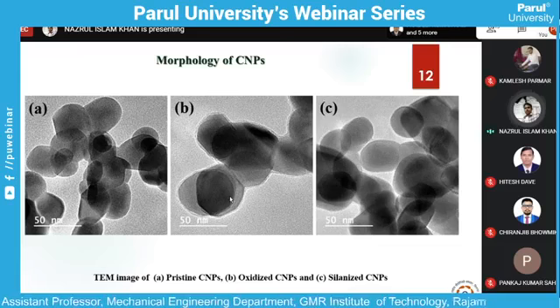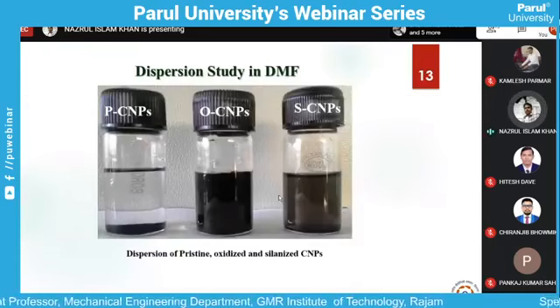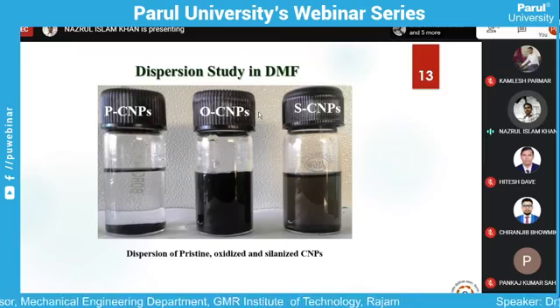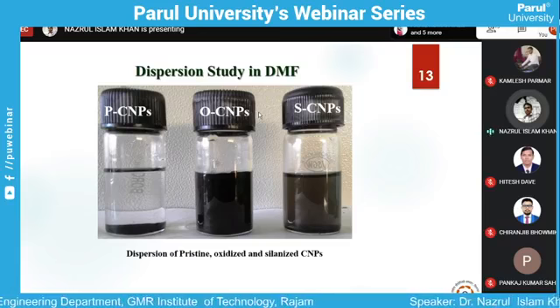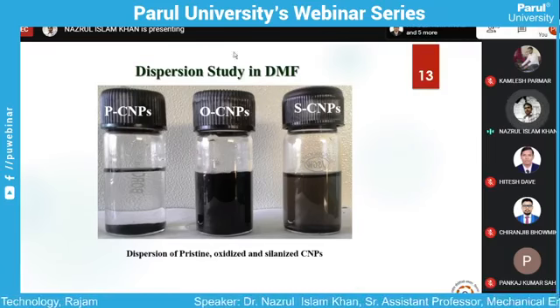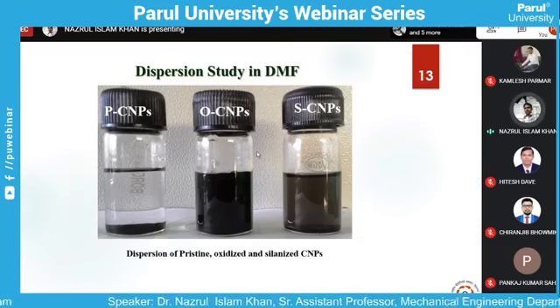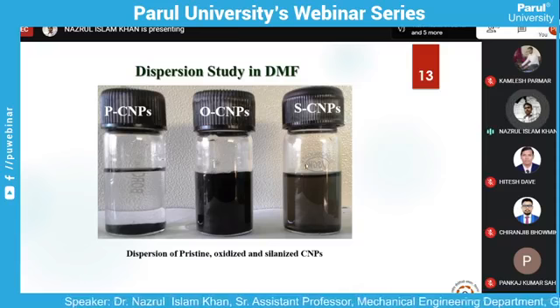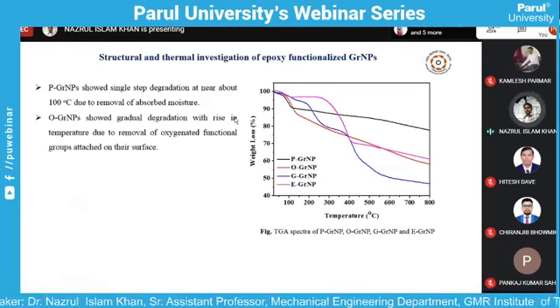This will also give you the indication that successful functionalization has taken place. Another very simple technique: if you want to check functionalization, first find out the polarity nature of the filler, and accordingly select a solvent to disperse them. If the polarity matches the solvent, and functionalization was successful, it will not settle. But if it has not been functionalized, it will get settled. This is called the dispersion test, and it also gives an indication of successful functionalization.